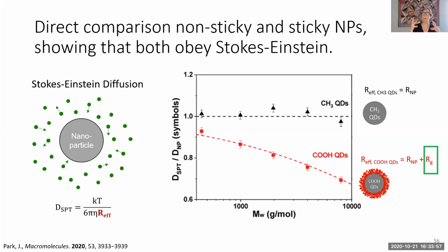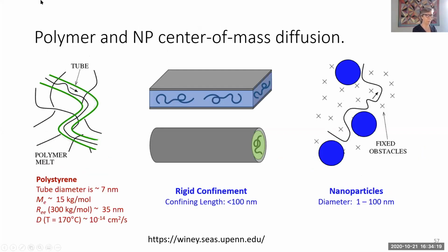Because that'll give us some insight about if the polymer chain is adsorbed for a very long time, it's unlikely the particles will agglomerate. But if the polymer is coming on and off that surface, that opens up a window for the particles to agglomerate and aggregate. So that's where we're headed next with polymer dynamics and nanoparticle dynamics.